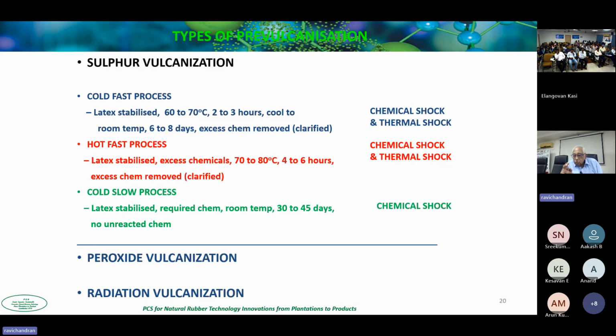Here, the latex suffers both chemical and thermal shock. We have the hot fast process where you can heat to 70 to 80 for 4 to 6 hours, remove the excess chemicals, and then you can have it ready within a couple of days. So here also there's chemical shock and thermal shock. In the cold slow process, we stabilize the latex, we add the chemicals, it's at room temperature. They're very slow room temperature curing chemicals, and we keep it for 30 to 45 days. And here there's only chemical shock. There's no thermal shock. And because of that, the latex is much more stable.